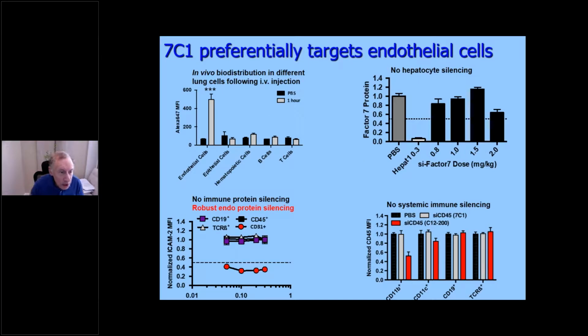And then if we go to the next slide, what you see is that, again, 7C1 preferentially targets endothelial cells. You see that on the first slide with a very high distribution. And here, which is interesting, you get no hepatocyte silencing, no immune protein silencing, whereas you get robust, if you go to the bottom left slide, robust endothelial cell protein silencing. So this was all very exciting, that you could now find lipid particles that would not target the liver and would target another cell type.